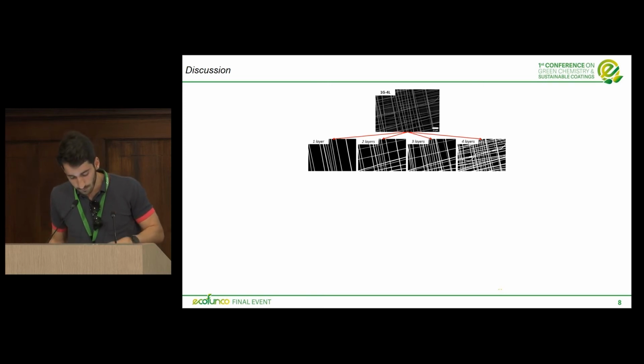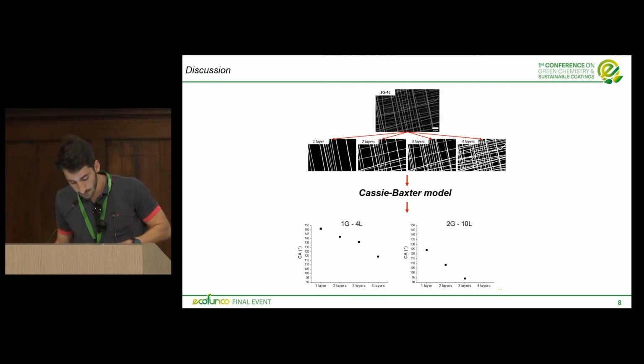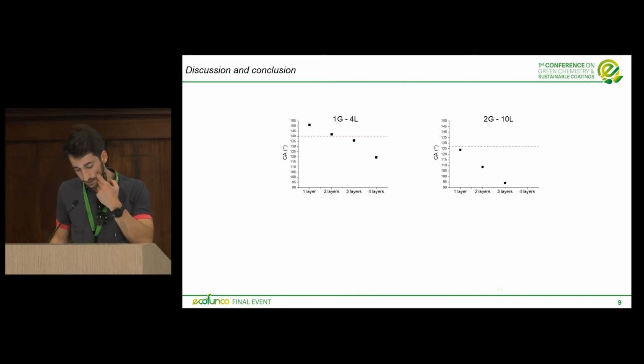After measuring the porosity of the 4 outermost layers, as I reported in this image, we measured with the Cassie-Baxter model the contact angle at equilibrium. So, for example, if we consider the first generation coating and the porosity given by the first layer, we calculated a contact angle of around 150. If we consider the porosity given by 4 layers in the first generation coating, the theoretical model gives a contact angle of around 120. So, if we consider the previous graph and outline in red the experimental water contact angle measures for the first generation and the second generation coatings, the data suggests a possible correlation.